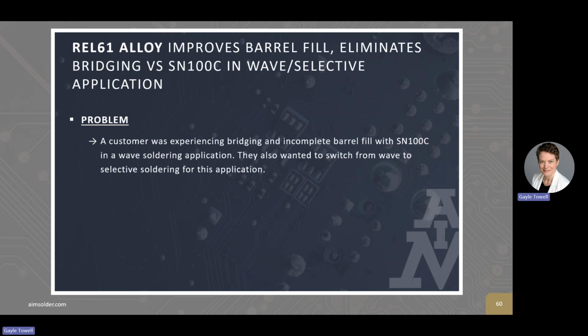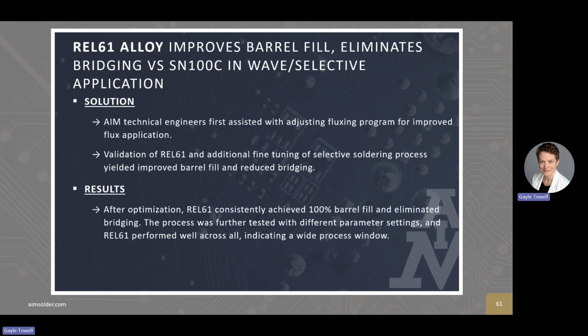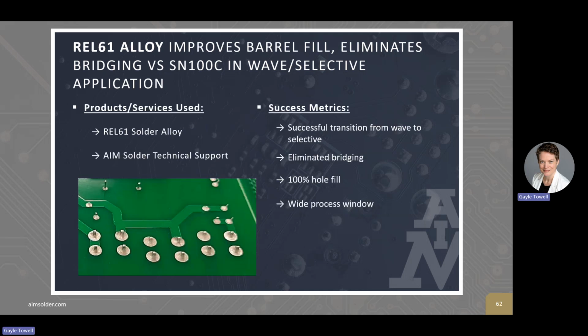As another example, it improved barrel fill and eliminated bridging compared to SN100C in a wave selective application. So they tried out our REL61. After optimizing everything, REL61 consistently achieved 100% barrel fill and eliminated bridging. And even with different parameter settings, REL61 performed well, which also indicated a nice wide process window. They were able to successfully transition from wave to a selective application. They eliminated all of the bridging problems, had 100% hole fill, and a nice wide process window.